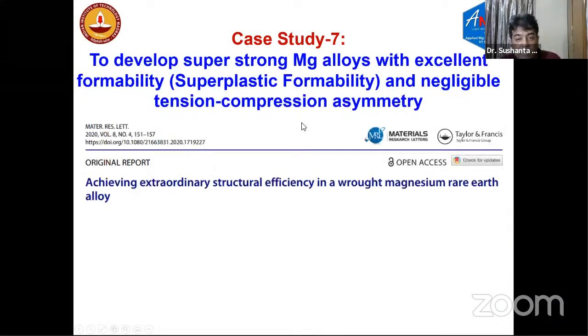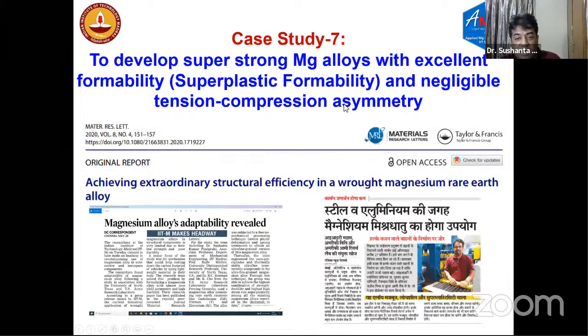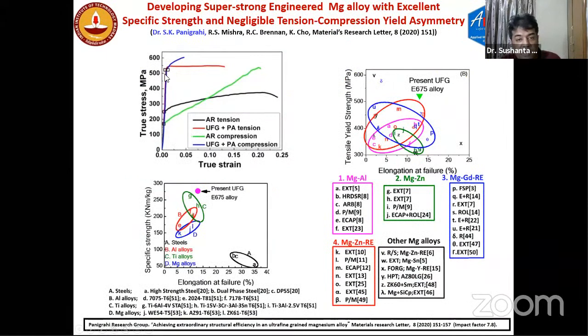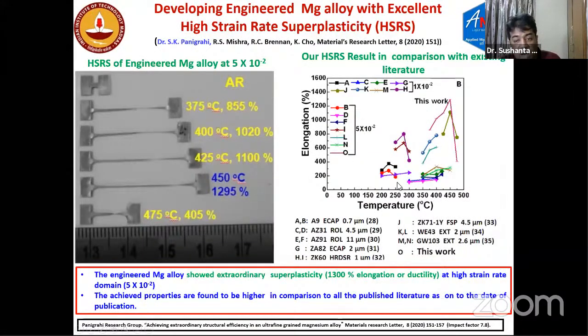Then recently we developed a super strong magnesium alloy with high strength, superplasticity, and negligible tension to compression yield asymmetry. You can see our developed material showed a strength of 500 megapascal, which is the highest among all the published papers in the market, and our material gave a superplasticity of around 1300% elongation, which is again the highest, at 5 x 10^-2 per second.